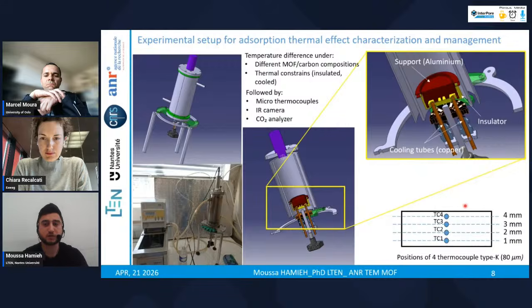Here, to measure the temperature inside the sample, we placed 4 micro thermocouples of 80 micrometer diameter at 1 millimeter from each other. And we can inject in this cylinder either pure CO2 or a mixture of CO2 and nitrogen. With this setup, we will measure the temperature difference for different MOF and MOF-carbon compositions, varying the percentage of carbon inside the composite. We will test this in different operating conditions, insulated or cooled.